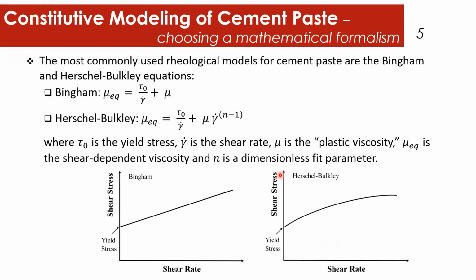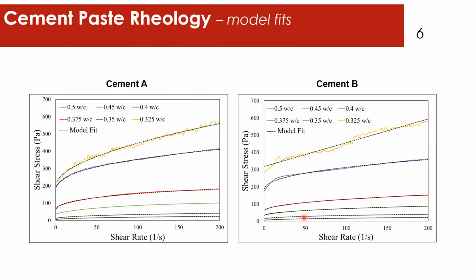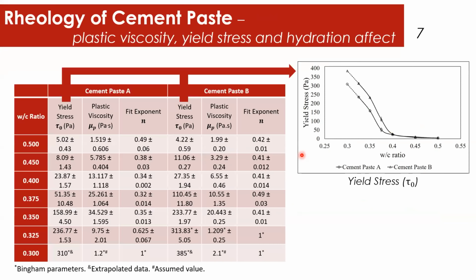I then fit that data set with either a Bingham model or a Herschel-Bulkley model, and I get these beautiful fits with the Herschel-Bulkley model for most cases, except for maybe this one case where it was a rather stiff paste, and it turned out to be Bingham rather than Herschel-Bulkley-like. That being said, I collect these experimental data, I do it in triplicate, and I determine the yield stress, plastic viscosity, and the fit exponent for both cement paste A and B.